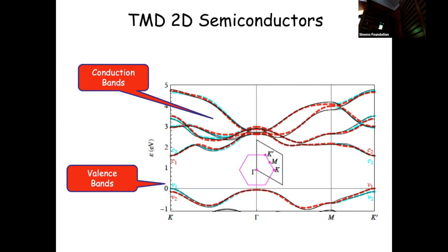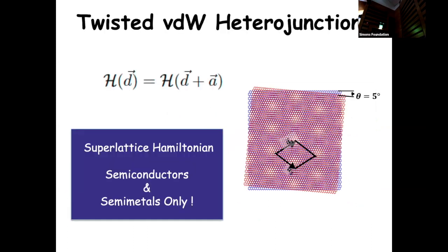In this case, for a single 2D sheet, you can see that the top of the valence band occurs at the corners of the Brillouin zone, at two inequivalent points in momentum space, which I'll refer to as valleys, related by time reversal symmetry. There's quite a substantial spin-orbit splitting between the two bands at the top of this. So mostly we'll be interested in physics on an energy scale smaller than this spin-orbit splitting, and so there's only one spin state at each valley, and the locked spin-valley degree of freedom acts like an effective spin. So a single layer is one band with a spin degree of freedom.